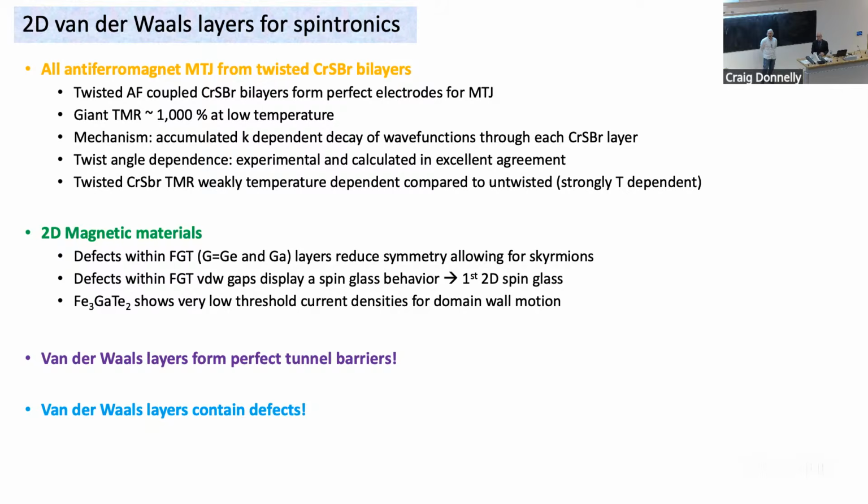So they're pinned at single defect sites then? Is that what you're saying? No, I don't think a single defect will pin the domain wall. The domain wall itself in these structures is of the order of a few nanometers wide, in the range of 6 to 10 nanometers wide. So you need a lot of defects to pin it, not just a single one.